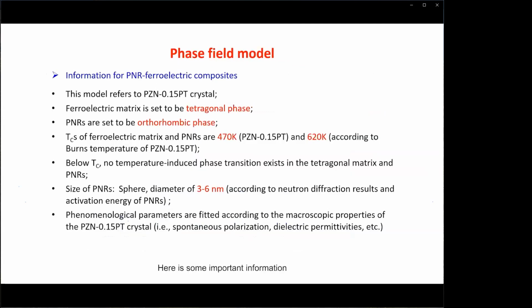Here is some important information for the nanocomposite. This model refers to the PZN-0.15PT crystal. The ferroelectric matrix is set to be the tetragonal phase. Polynanoregions are set to be the orthorhombic phase. The Curie temperatures of the ferroelectric matrix and polynanoregions are 470 Kelvin and 620 Kelvin. Below the Curie temperature, no temperature-induced phase transition exists in the tetragonal matrix and polynanoregions. The size of polynanoregions is set to be around 3 to 6 nanometers.